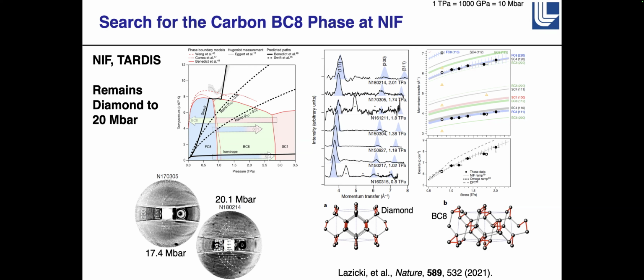I just had a question. I was staring at the current slide and I saw the data you have on the diamond as a function of pressure, and you have the real data there, and there's bluish purple colored features on the graph, which I guess are showing what you would expect from the calculated structure, so you can compare that with the data. That's right. And I'm seeing that the 220 and the 311 are visible, but very weak relative to what you expect. Is that just a massive thermal motion effect?